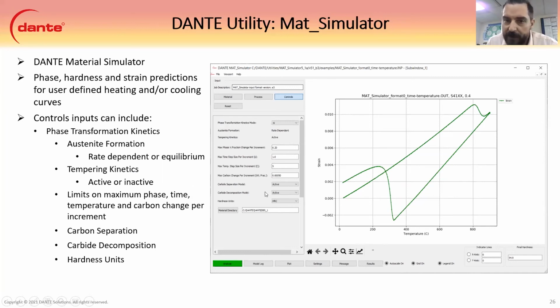We also have a carbon separation model. So when you transform to ferrite, you get a carbon rejection, and that has an effect on the martensite start. It'll make it lower if you have more carbon. And then you also have carbide decomposition. So if you start initially with carbides, you decompose and you have a higher carbon level in the austenite solution before quench. And then you can change your hardness units from HRC to Vickers.